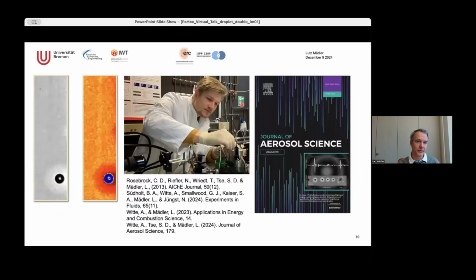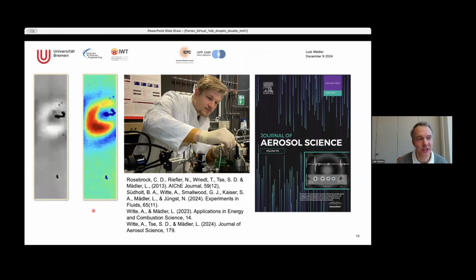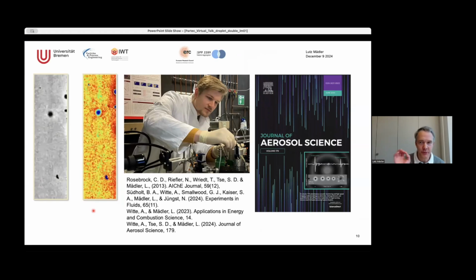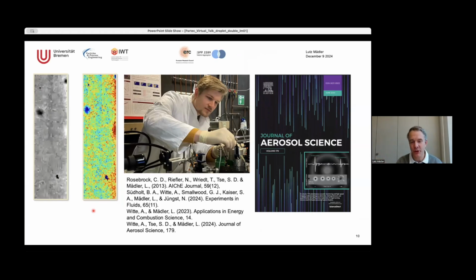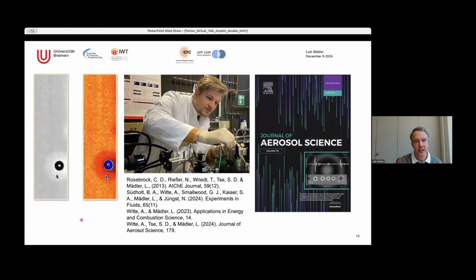And this is done here with Malte, with Arne. And Arne is working on single droplet experiments, and he looks very closely at these experiments here. So we're looking into these explosions and seeing what these precursors are actually doing, if they are set free at the same time or not. And Arne here is doing exactly this. What he has developed is a method to actually listen to the droplets when they explode, and also look at them. So what you see here is a flame around the droplet. The droplet is in the middle. And at some point, the droplet explodes. It's exactly now. And then he listens to it with a microphone.